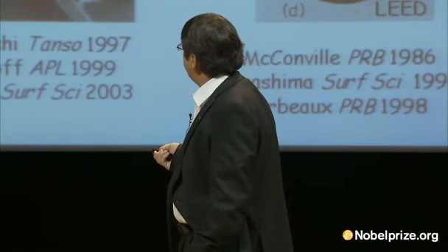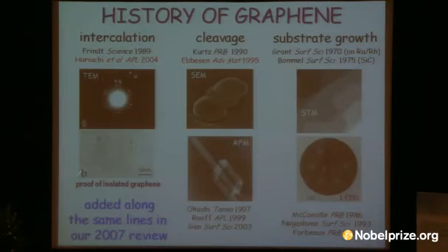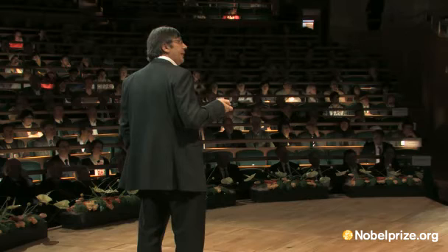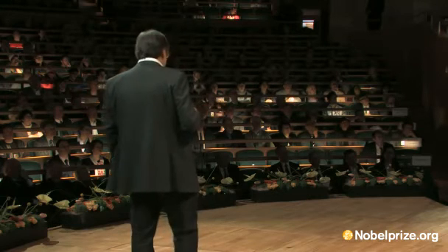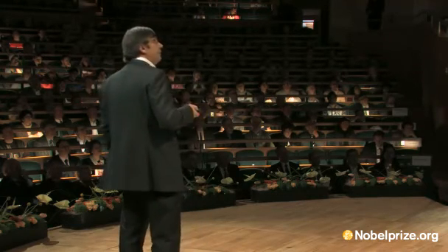So I think the closest observation of isolated graphene was in a paper by Ohashi, where they observed in TEM folds of graphene which correspond to a single layer. Also Ebbesen in '95 made something like origami, still several layers thick and on top of graphite, but it was a very close attempt. Several people grew single layers of graphene, but they were still coupled with the substrate and not isolated. So whom should we attribute the discovery of graphene to?